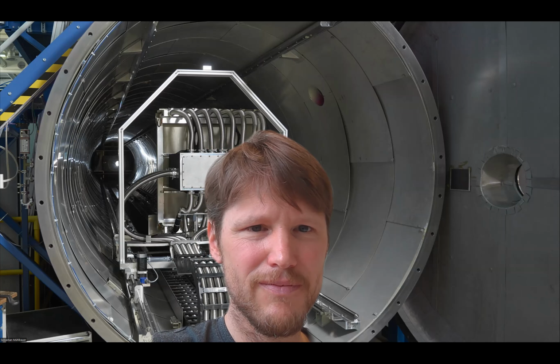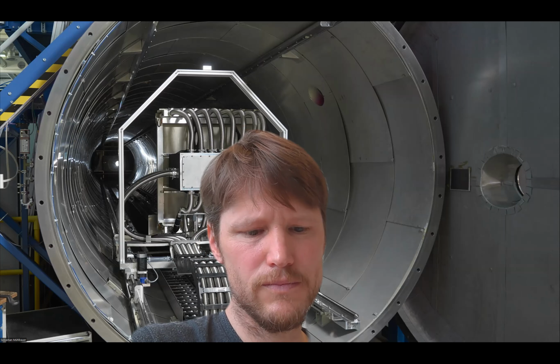So first of all, it wasn't developed by me, it was developed by one of our collaborators, Dr. Alex Holmes. And basically the reason for using Bayesian analysis to better visualize vortex lattices is, as we mentioned before, we have a lot of noise. When rocking a sample, depending on the rocking direction that we are using, a specific reflection can be rocked many more times than the rest, and then the intensity is not going to be completely homogeneous for the whole vortex lattice.